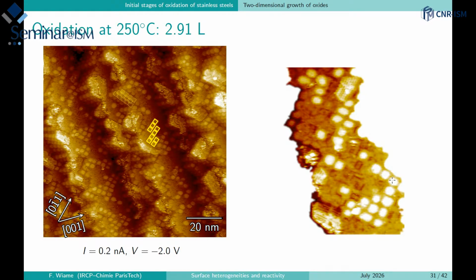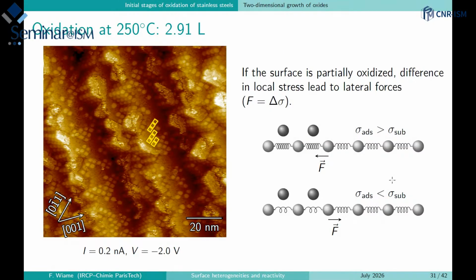This is again related with the surface stress, because here, for example, if you are adsorbing some oxide, let's say, on your metal surface, then you will have an electronic redistribution, so you will change the force. If you change the force, then you will have some point force that will appear. If you increase the interaction, then the force will be this side. If you decrease the interaction between the metallic atoms, then the force will be opposite. But this is for the same reason that we will have this self-organization of the islands at the surface.